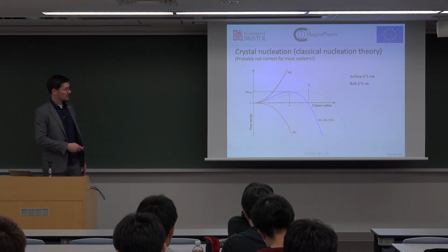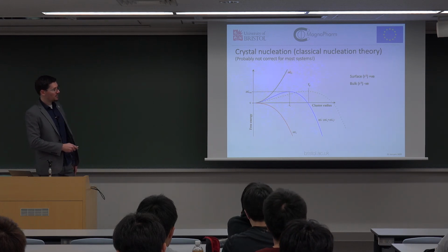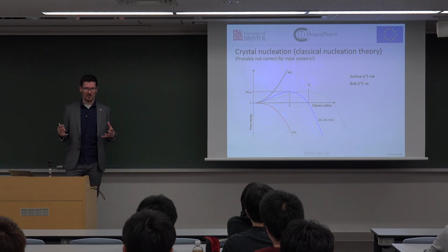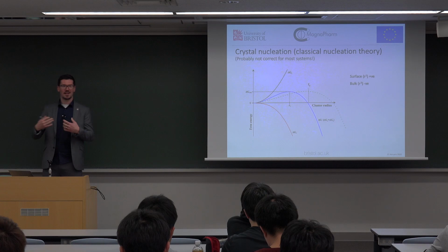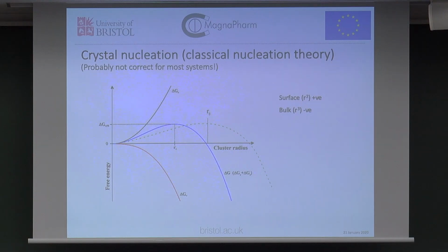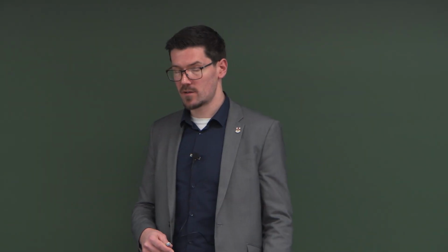Basically, the idea is the surface of a particle is an unfavorable environment. The bulk is favorable, energetically speaking. So as our cluster gets bigger, we end up with this, because the surface is reliant on r squared and the volume on r cubed. We have this blue line here, which is a summation of the two. So here we have what's called the critical radius, which means as soon as it gets that size, it becomes more favorable to get bigger than smaller. So when crystals start to grow, they grow.